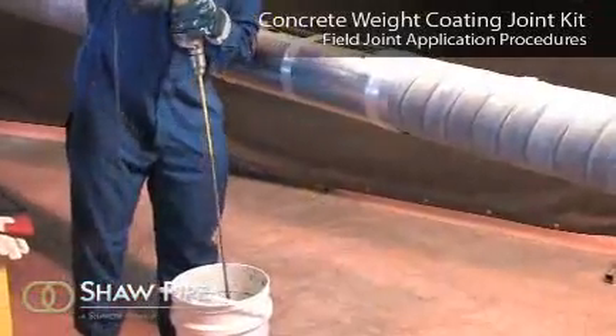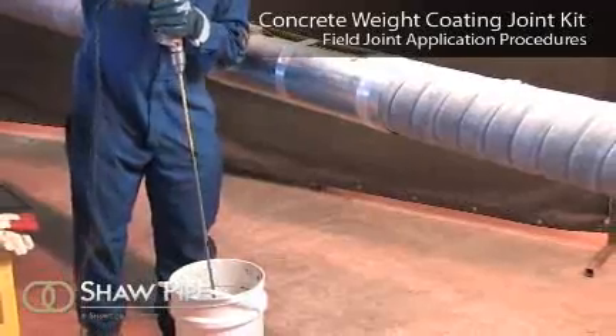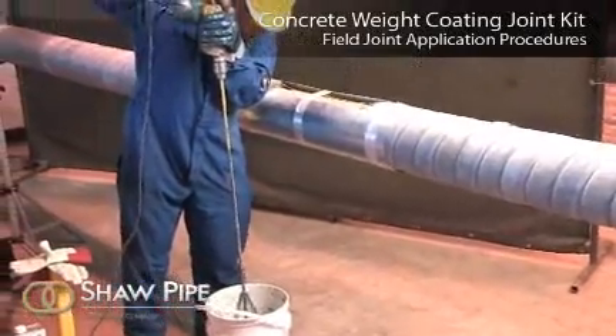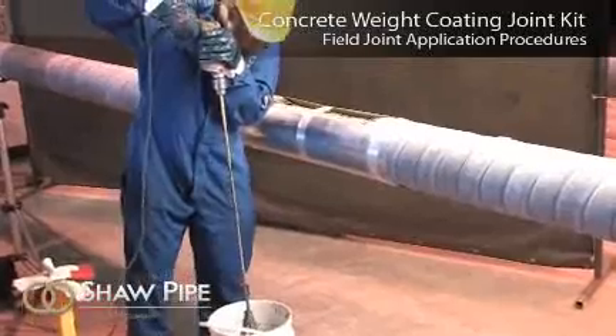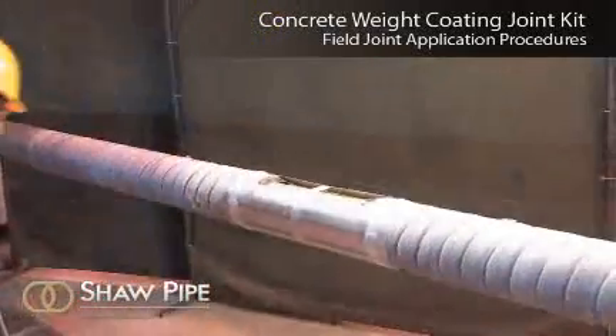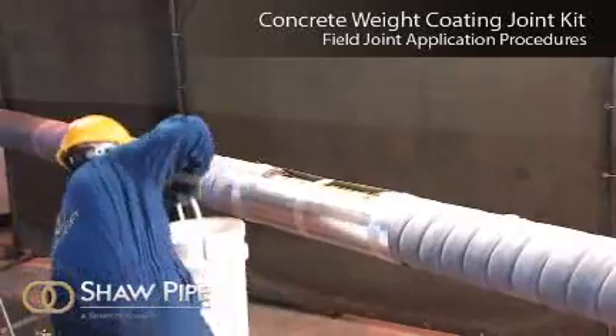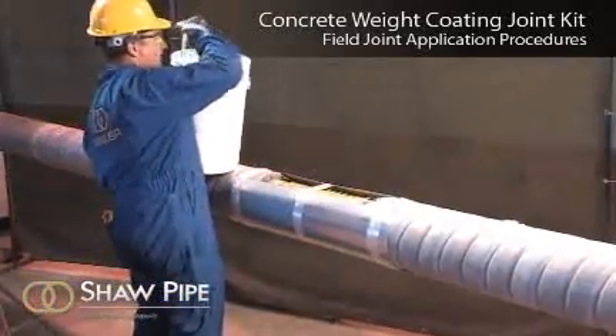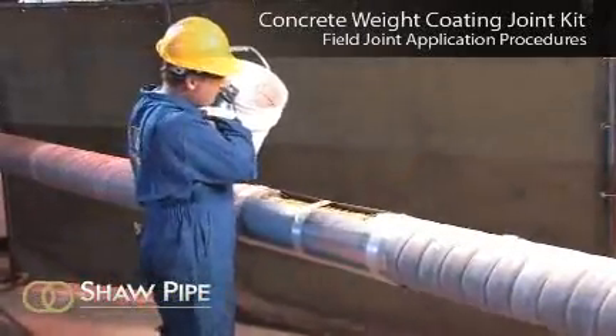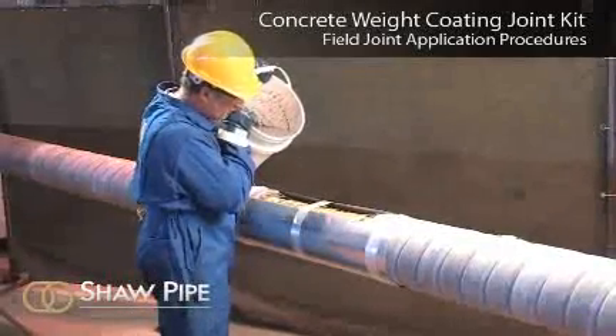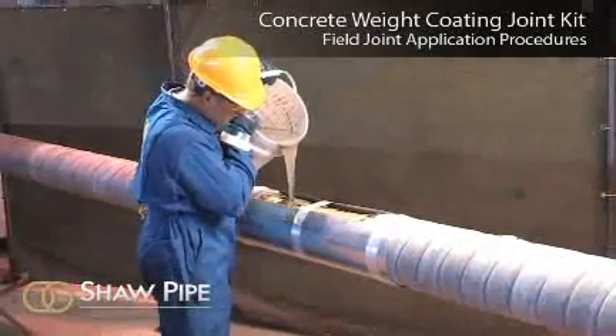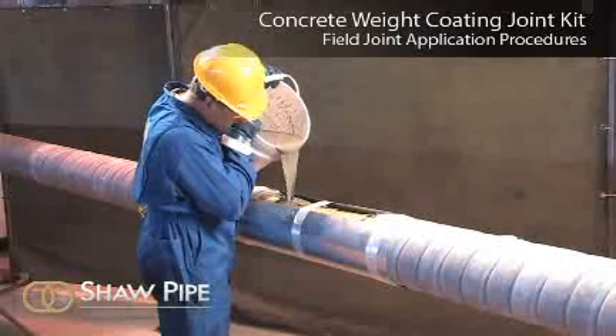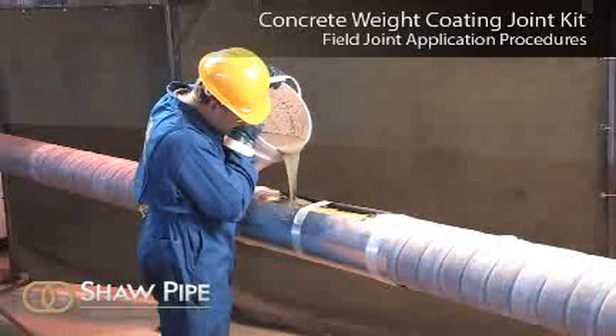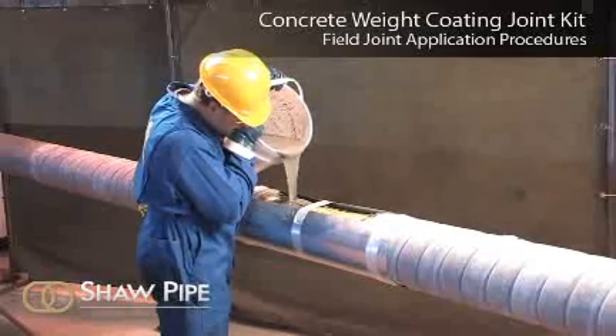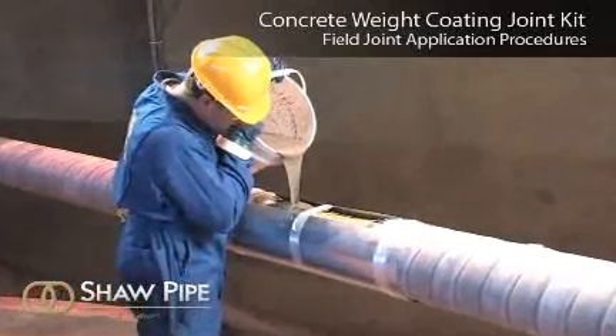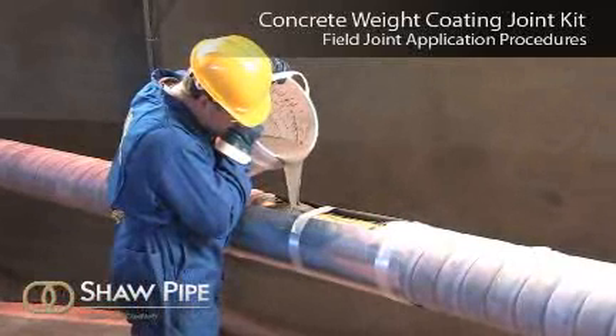Mix the joint material either in a mechanical mixer or by hand, according to the following instructions. Add water to the mixer first. The amount of water will vary between 3.75 to 5 liters per 25 kilogram bag of grout, depending on the grout consistency required. Start with 3.75 liters per bag initially. More can be added later if a more fluid consistency is required. Add the dry grout mix to the mixer. For example, a 16-inch pipe with 1.5 inches of concrete and 8-inch coating cutbacks would require approximately 2 bags of grout per joint.